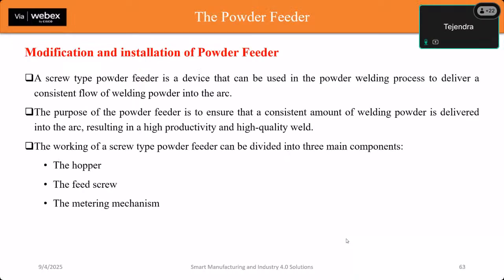Once the cooling bed was formed, we also modified the powder feeder that has been bought from the market. So in operation, the feed screw rotates at a constant speed in the powder feeder, delivering a consistent flow of the welding powder from the hopper to the metering mechanism. The metering mechanism regulates the flow of welding powder into the arc, ensuring a consistent flow rate. This directed flow produces a high quality weld.